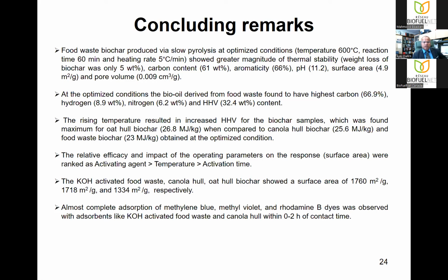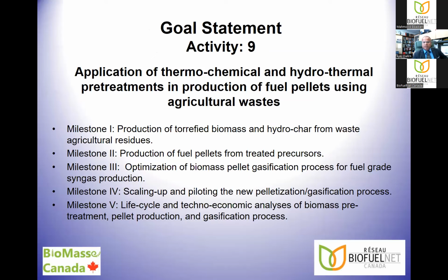And when we activate this material, we found that the activating agent has a better impact than the temperature and activation time to get a better product. We also looked at the methylene blue, methyl violet, and the rhodamine B dye adsorption using the potassium hydroxide activated food waste, and also for the canola hull as well, and they are very, very effective. So let me go to activity 9, then we can maybe have some discussion at that point.